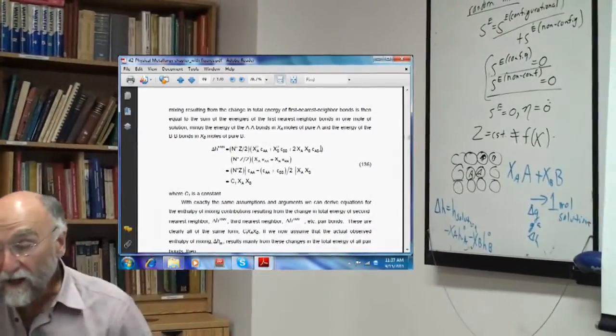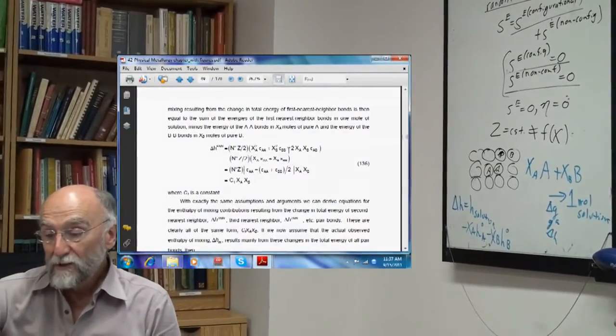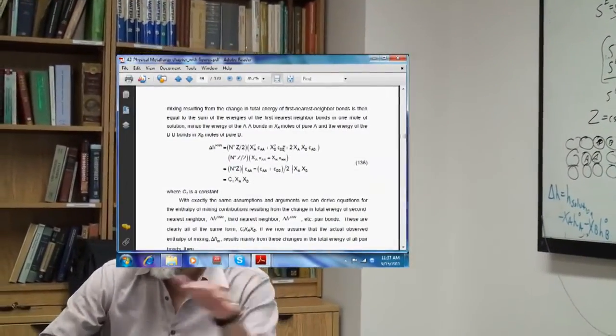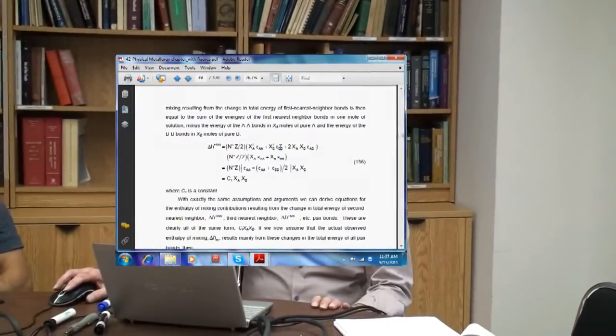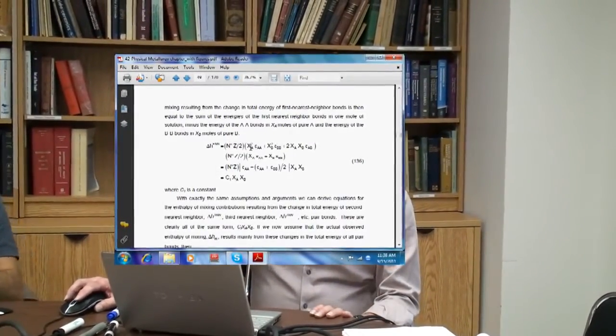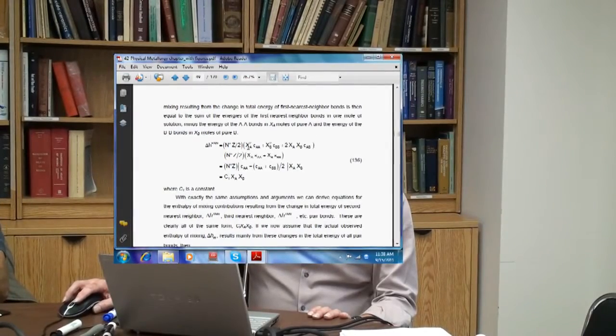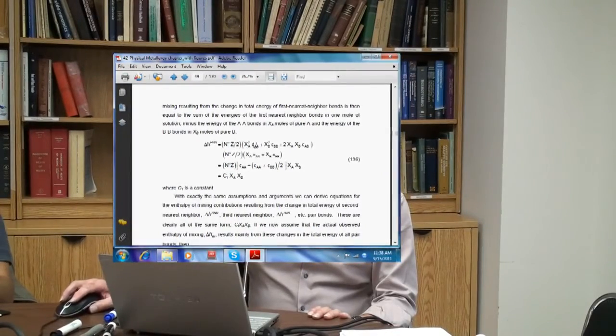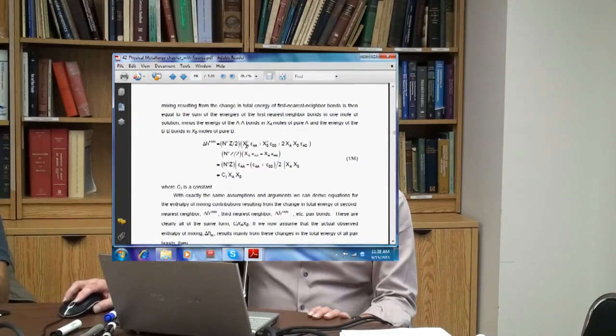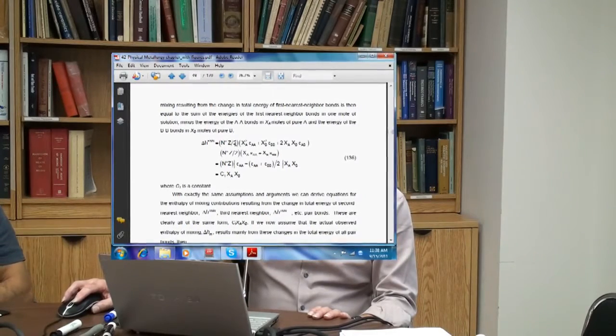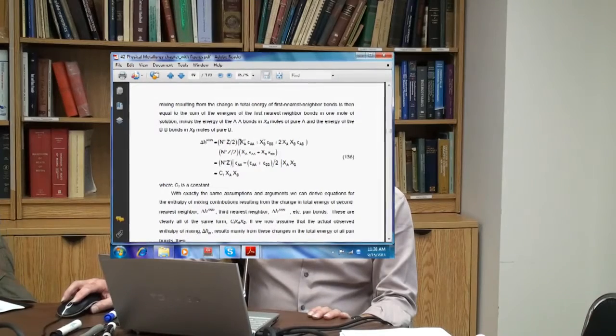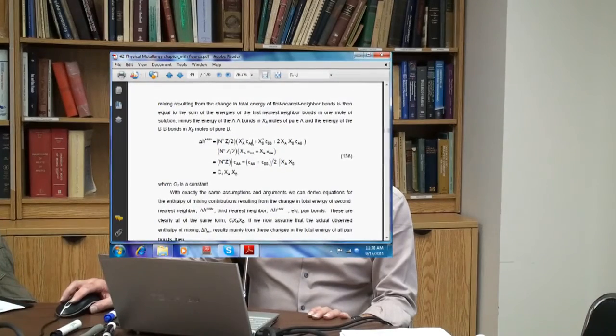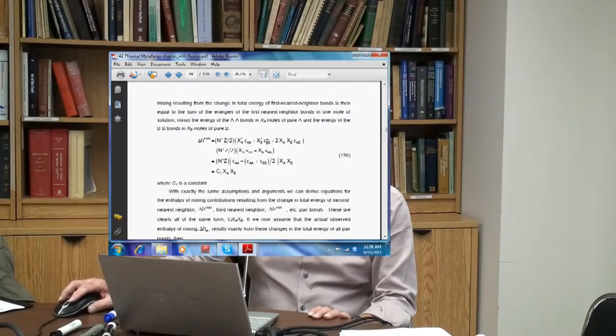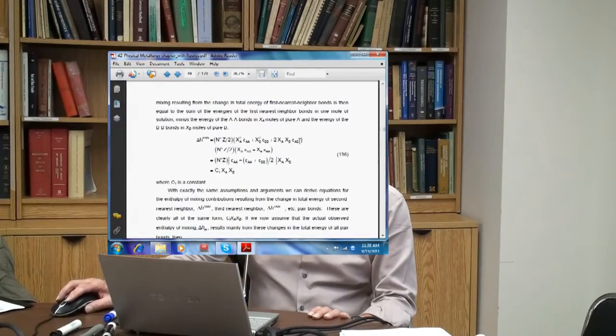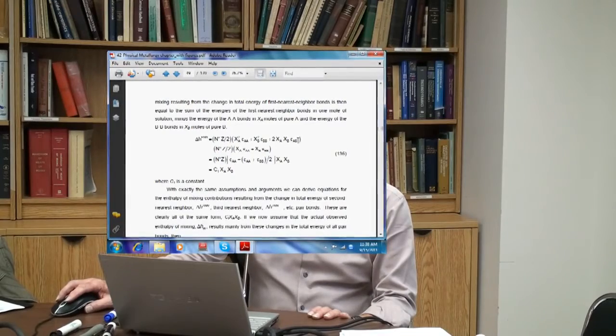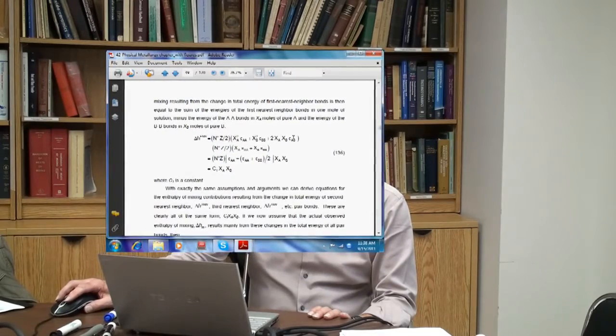Epsilon AA is the energy of an AA bond. Epsilon BB is the energy of a BB bond, and so on. And this is independent of the composition, from pure A to pure B, and of temperature as well. So the energy of this first term here is the energy of the first nearest neighbor pairs. That's how many first nearest neighbor pairs you have. That's the probability that it's an AA pair, that's the energy of the AA pair. This is the probability that it's a BB times their energy, probability of the AB pairs times the energy of the AB. So that is the energy of the first nearest neighbor bonds in 1 mole of solution.